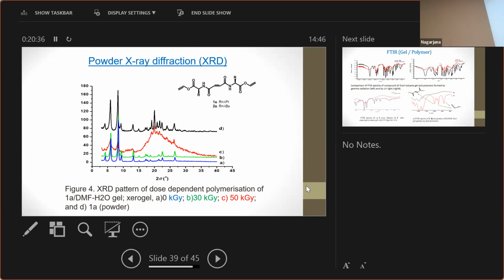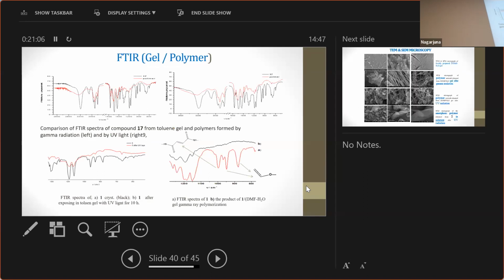After 50, it's about 1-2 hours. Our samples become somewhat disordered in peaks, which comes from a new structure. Okay. Also, we follow the reaction with IR spectra. Here is the example. The red line is the spectrum of the starting materials. We see a group of vinyl peaks, and after polymerization, these peaks disappeared. It's evidence that we obtain a polymer.